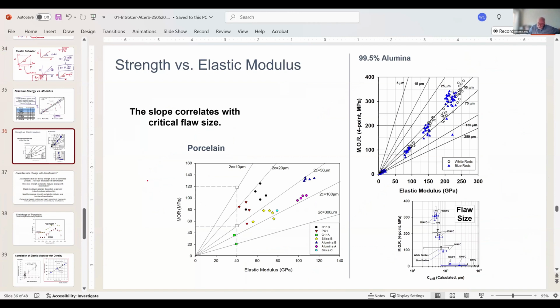And what we find is that elastic modulus, here, strength versus elastic modulus, this is strength over here. And I get a series of curves. There's a series of them in here, and the lines represent flaws. As I go in this direction, my flaw size is decreasing, okay? And you can see here's a group that has a change in elastic modulus.